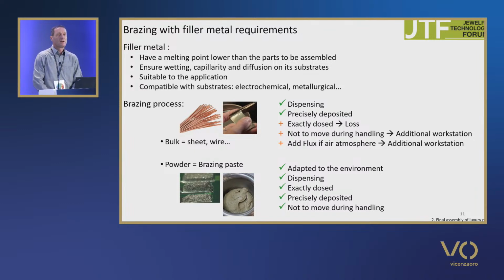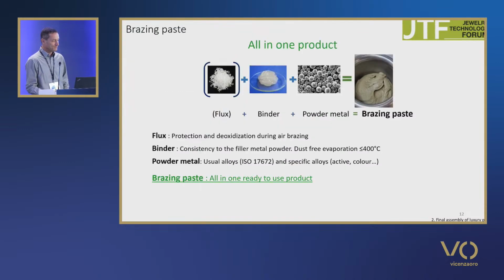The brazing filler metal requirements. The key points for filler metal is melting point, which should be as high as possible, but not too close to the component's melting point. Suitable to the application means the right metal, first the right metal fineness for 18 karat gold, the right color or the closest color possible, and the mechanical requirement for luxury goods.